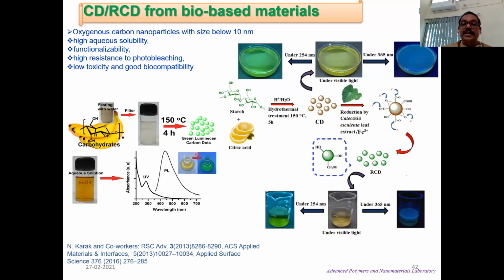We have used a very simple strategy, and this paper is still now one of our most highly cited papers, where we have synthesized this green luminescent carbon dot from banana juice or any water soluble carbohydrate, just by heating 4 to 5 hours at 150 to 160 degrees centigrade, even in a glass container. This carbon dot, whether obtained from starch, banana juice, or any other carbohydrate, can also be reduced to get more effective fluorescence, and particularly this material has a good photocatalytic effect, which I shall discuss later on.